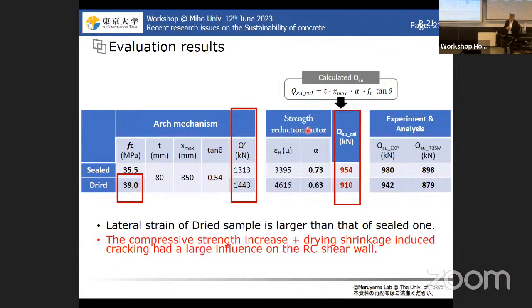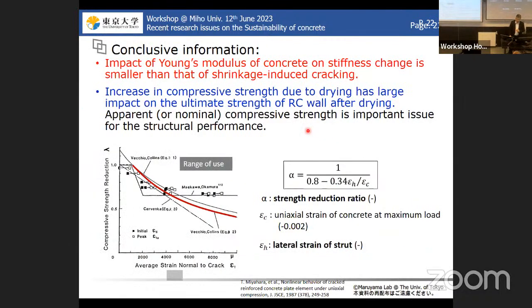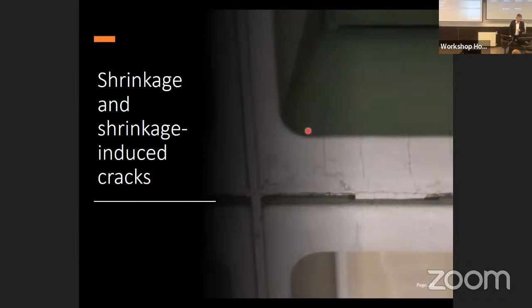So actually, many researchers say that the compressive strength can be reduced by the drying, and some other researchers say that the strength of concrete can be increased by the drying. But actually, this non-consensus state comes from the type of aggregate used in the concrete for experiments. And so I think the material property used for concrete is very important. So I would like to talk a bit about this. So now I move to the shrinkage and the shrinkage induced cracks.